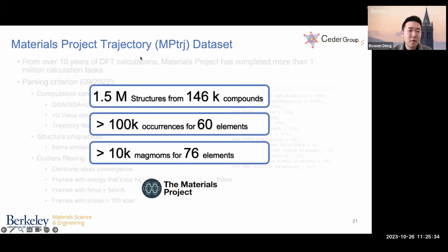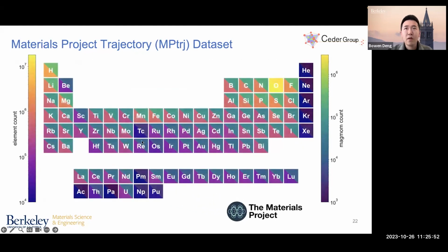So by this effort, we reached 1.5 million structures from these 146K compounds from Materials Project, and we achieved more than 100K occurrences for 60 elements, with more than 10K magmoms for 76 elements. And here is the distribution of the elements within the MP trajectory dataset. You can see we have considerable coverage of almost all chemistry, excluding only the noble gases and actinoids.